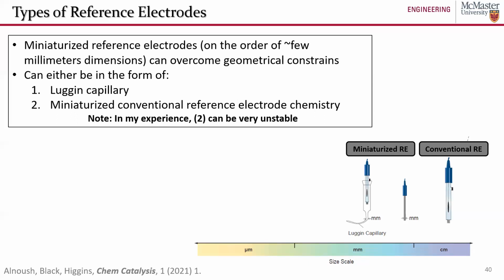And so these miniaturized reference electrodes can come in 2 forms. One is by using a Luggin capillary, which I look at essentially as an extension cable for a reference electrode. It's just a small plastic tube with a glass frit on the end that you can fill with a reference electrode fill solution and essentially extend the sensing area of your reference electrode into a small electrochemical cell, for example. Or there are commercially available miniaturized conventional reference electrodes. For example, miniaturized silver chloride reference electrodes that have 1 to 2 millimeters diameter.